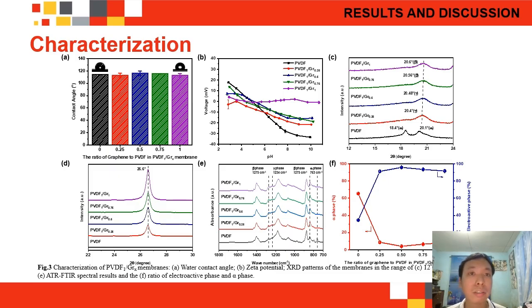Characterization. Figure A. The water contact angle of the PVDF membrane is 114.2 degrees, and the addition of graphene only slightly affects its hydrophilicity, maintaining the angle between 113.1 degrees and 116 degrees. This indicates that the membrane's hydrophobicity remains stable, ensuring consistent interactions with water. Figure B. For the zeta potential, the PVDF membrane surface potential shifts from 17.67 mV at pH 3 to negative 33.51 mV at pH 10. The addition of graphene reduces the pH sensitivity, with PVDF1 graphene 1 showing surface potentials between 4.07 mV at pH 3 and negative 0.96 mV at pH 10.